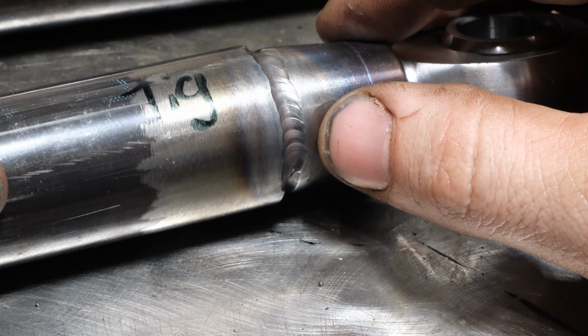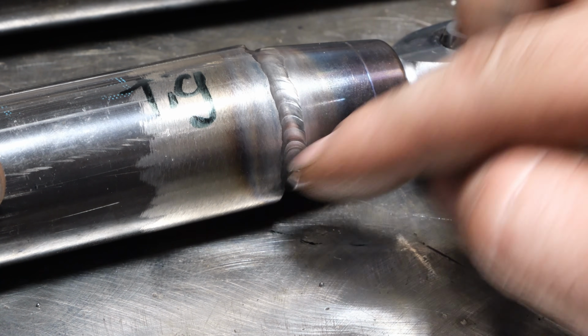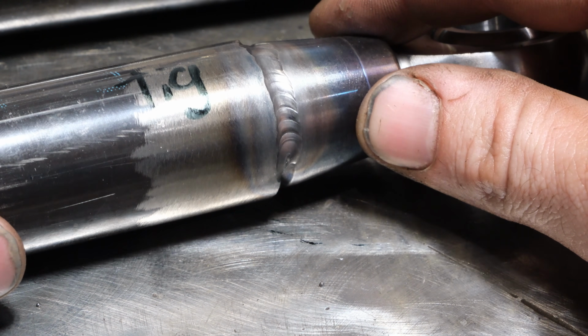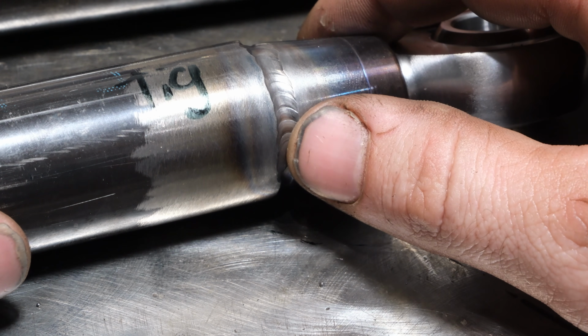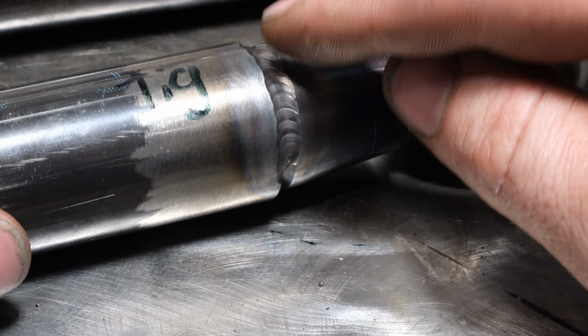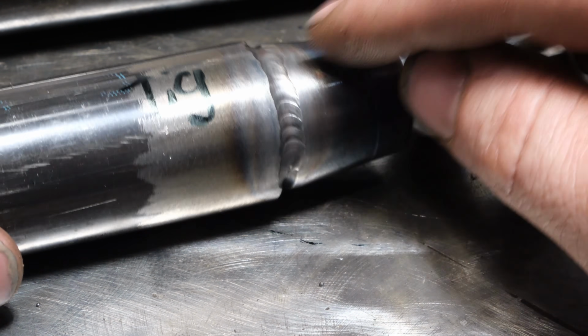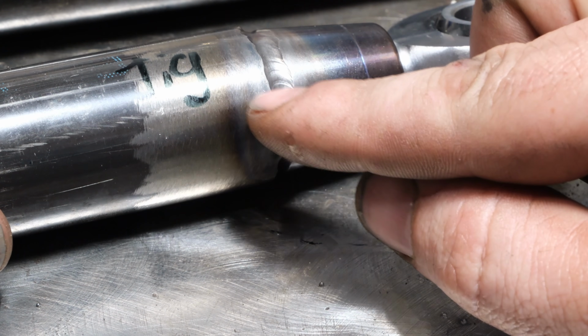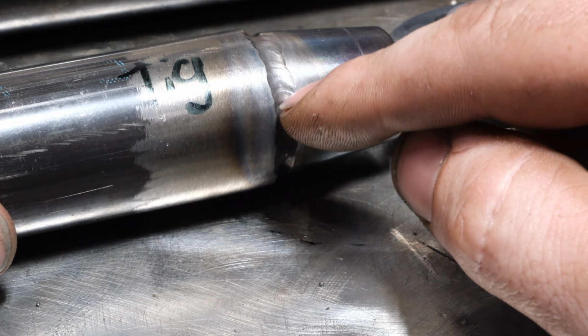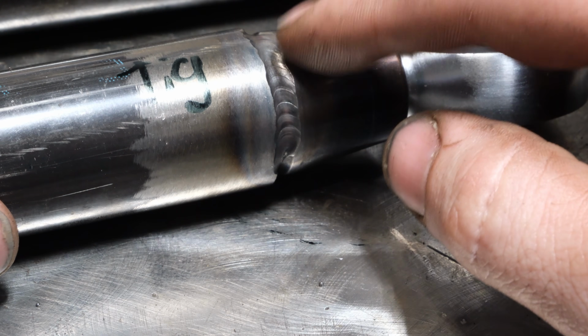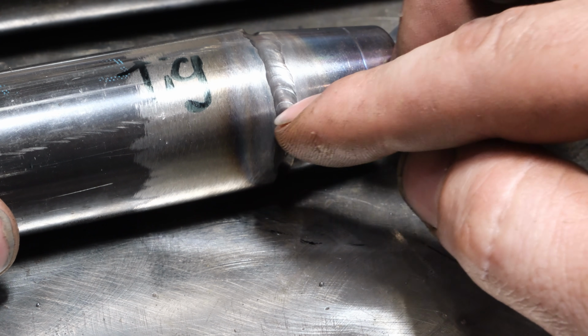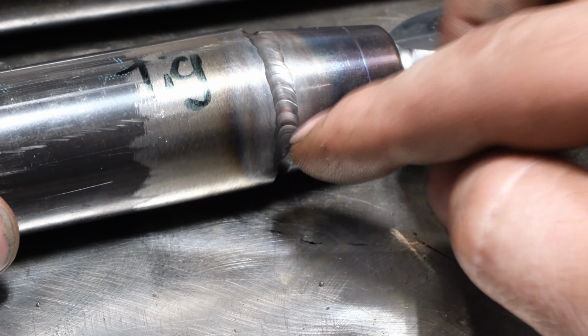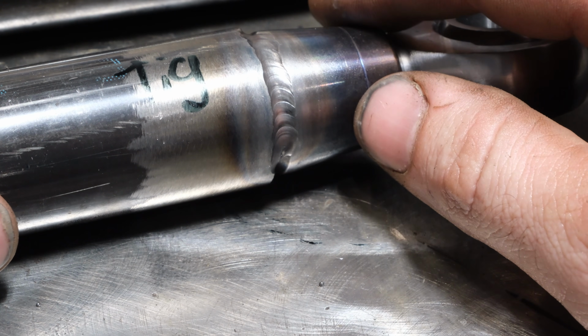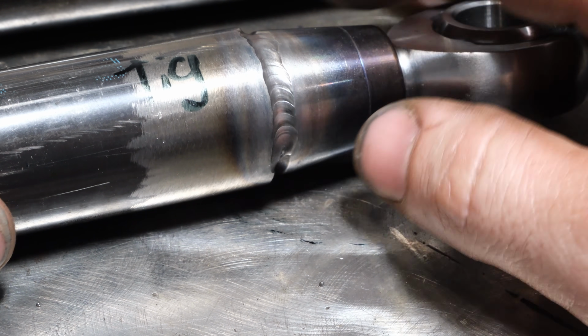The next weld I did was a TIG weld. I did a single pass running pretty hot, somewhere around 160 amps with 1/16 filler. Generally not what I would do, and the reason is simple. This is essentially all underfilled. I would never weld this with TIG with a single pass. I would go back and do a second pass over this because the throat depth of this weld is going to be on the thin side, and we should see that in the cut and etch.